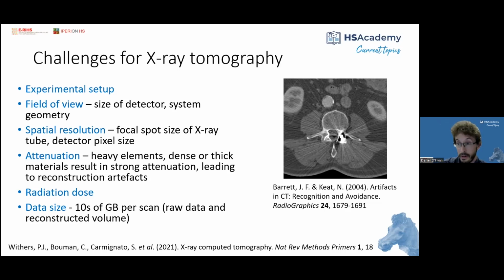The radiation dose is a very important thing to consider. We often refer to X-rays as non-destructive, but they're not truly non-destructive. Very high radiation doses can cause damage to objects or to remains of humans or animals. So, for example, X-rays could cause discoloration of materials, and at very high doses, they could cause damage to DNA structures in humans or animal remains. So there's a lot of research to be done to further understand these effects. And we definitely don't have all the answers right now, but I think we definitely need to exercise caution when using X-rays with heritage material.